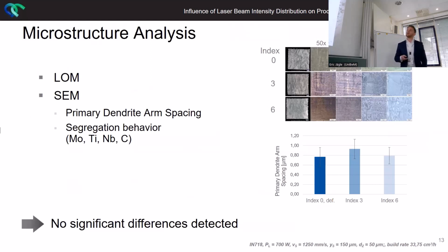And for that, we had a look at the microstructure at a coarse microscopic scale, light optical microscope of edge cross sections, as well as the SEM image analysis of primary dendrite arm spacing and the segregation behavior. Didn't reveal any big significant differences, so the primary dendrite arm spacing was almost the same. And that got supported by another thermography video.